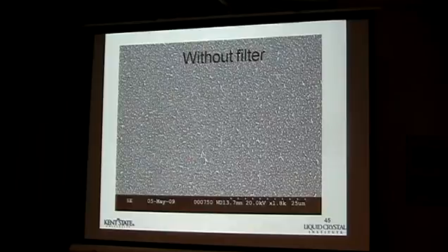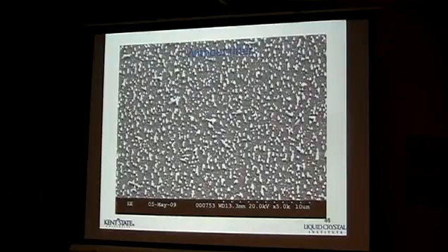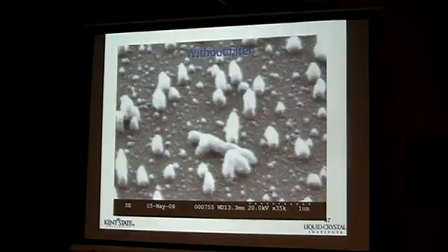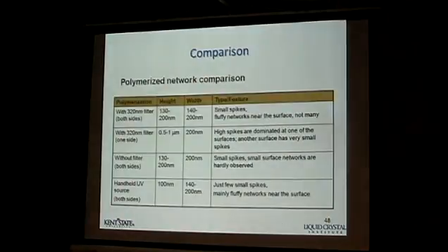So you can see this. You see the domain size is a tiny bit larger. Always enlarge that a little bit. This is 10 micron scale, so that's about 1 micron. You see that? So each domain is more like a candle. If we continuously enlarge that, that's about 1 micron, and roughly they are about 100 to 150 nanometers.